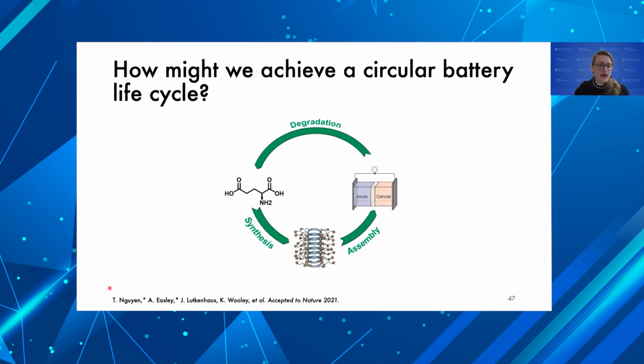So Tan Nguyen and Karen Woolley designed a polypeptide molecule that has redox-active groups hanging off the side that can act as cathodes or anodes. So the idea here is that you can take amino acids, synthesize them into polypeptides and functionalize them with redox-active groups. And then in my group, we assemble them into a battery where the polypeptide is the anode or the cathode, and then we use a metal-free non-aqueous electrolyte to comprise the battery.